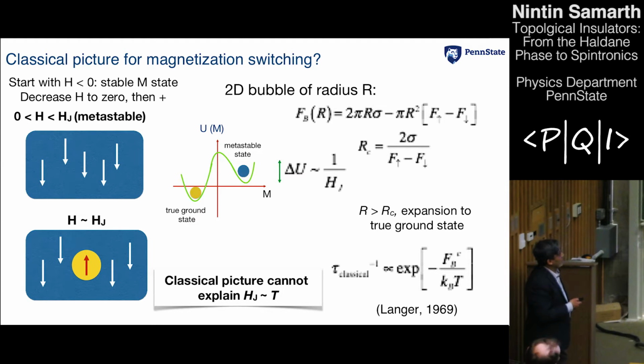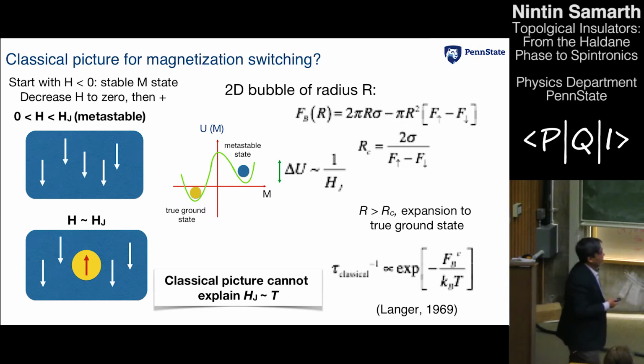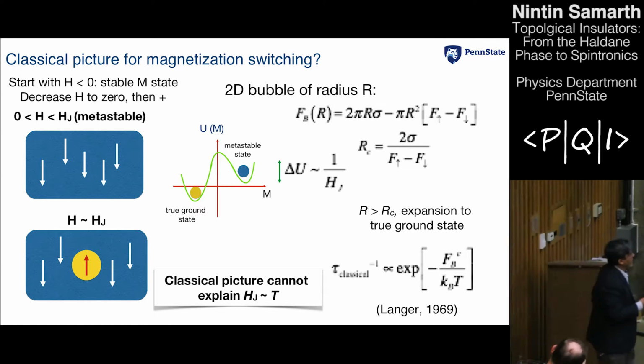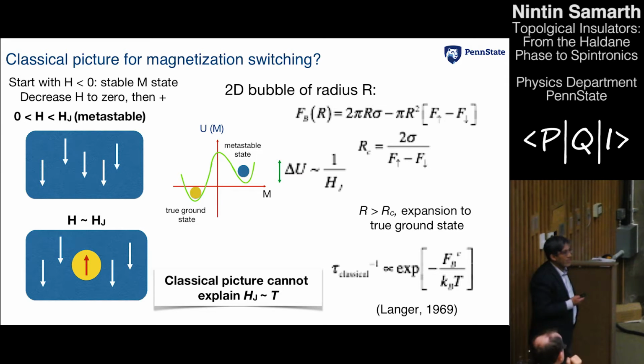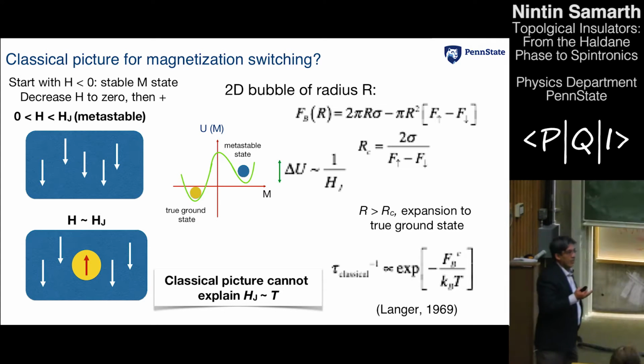And the way to think about it is that imagine that the metastable state of the system is in some state of magnetization over here, and then here's the true ground state, and the question is, how does the system go from here to here? Is it simply thermally activated, or is it something else, right? And if you just follow through in this kind of argument, then you can easily argue that the rate at which this process is going to occur is going to be such that, if you are using this field, which initiates the jump, as a measure of this activation process, then there is no way to explain this process in a purely classical way. So in other words, Hj, that jump field, cannot be increasing as you increase your temperature. The argument would go that it has to actually decrease, and we are seeing just the opposite.